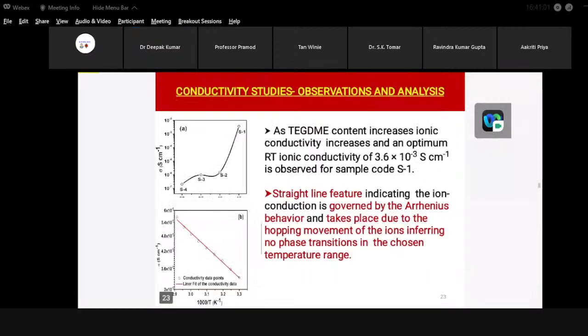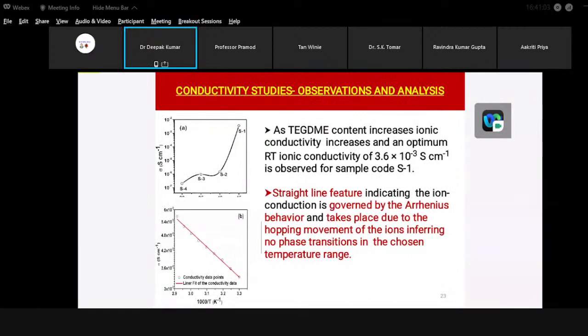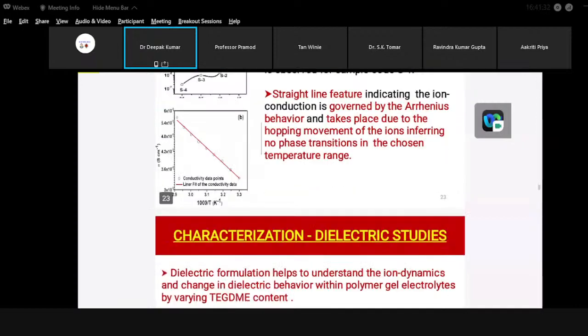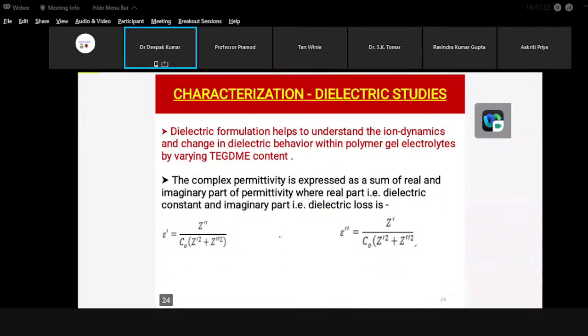For this electrolyte system also we have performed the conductivity studies, and the electrolyte composition having the highest TEGDME content is able to provide an ionic conductivity at room temperature of 3.6 × 10⁻³ Siemens per centimeter, and a straight-line feature which is governing the hopping behavior of ions and also indicating no phase transition because no such abrupt peaks are there. So this is also a good feature of the electrolyte system. To further understand the ion dynamics, we have performed dielectric studies also, and such formulation helps in understanding the ion dynamics and the change in dielectric behavior within the polymer electrolytes.